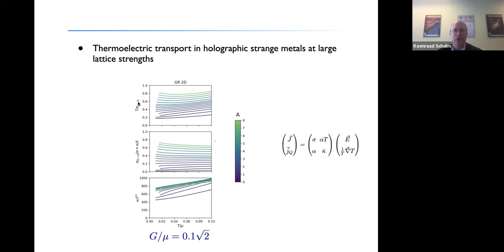But there's one thing that you should notice, that there is a large part now. This is the sigma Q is 0 part. This is the conductivity in the absence of a heat current. And here you see the ratio of the conductivity as a function of the heat current compared to the ordinary conductivity. And what happens is that its contribution as A increases becomes stronger and stronger.